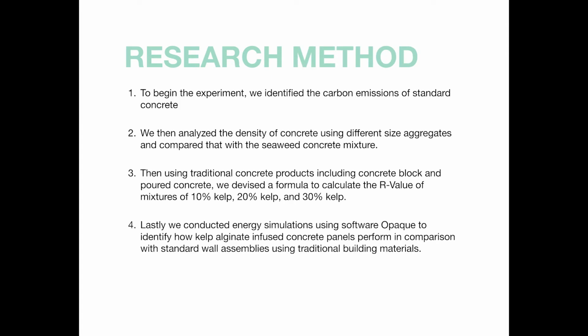And here are our research methods. To begin the experiment, we identified the carbon emissions of standard concrete. We then analyzed the density of concrete using different sized aggregates and compared that with the seaweed concrete mixture. Then, using traditional concrete products, including concrete block and poured concrete, we devised a formula to calculate the R value of mixtures of 10%, 20%, and 30% kelp. Lastly, we conducted energy simulations using software Opaque to identify how kelp alginate-infused concrete panels perform in comparison with standard wall assemblies using traditional building materials.